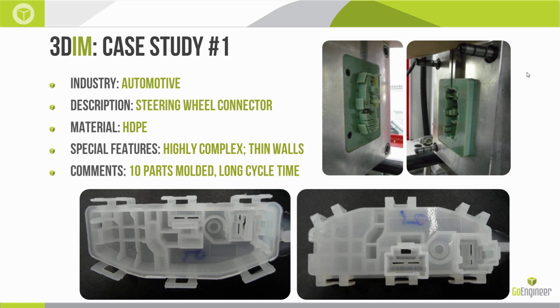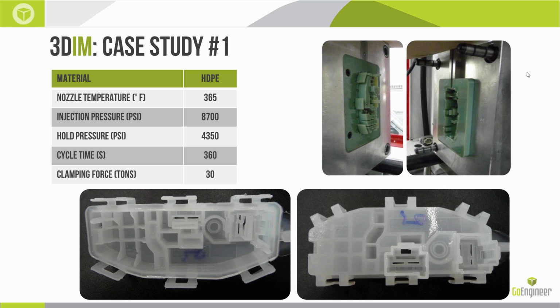So some stats on this. Nozzle temperature of 365 degrees. That's obviously higher than the heat deflection temperature that we list for digital ABS, and that's going to be consistent across the board. Pretty much the lowest temperature you're going to be dealing with in injection molding is 350 degrees Fahrenheit. Injection pressure, 8,700 PSI. Hold pressure of 4,300 PSI. So we're injecting that plastic at almost 9,000 PSI, and then once it's full, we're going to hold pressure on that, 4,300 PSI. The two halves of the mold are clamped together at 30 tons. That's actually on the low end of a professional level machine, 30 tons.